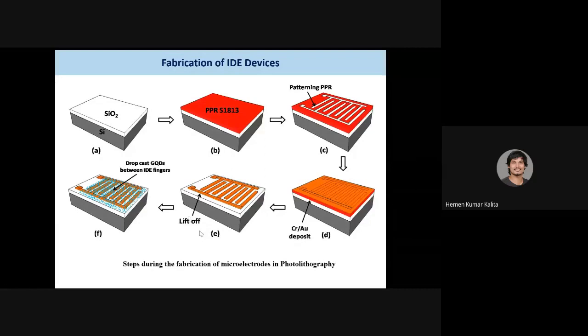Lift off process means only gold will remain and the photoresist will be removed from the device. Finally, after E, we deposited drop cast GQD on the fingers. These are IDE fingers. If you see this F, this is just a pictorial diagram to show how quantum dots are deposited on top. These two portions are the contacts. The small square portions at the edge are the contacts where electrical connections are done. So these are the fabrication steps of fabricating electrodes via the photolithography method.